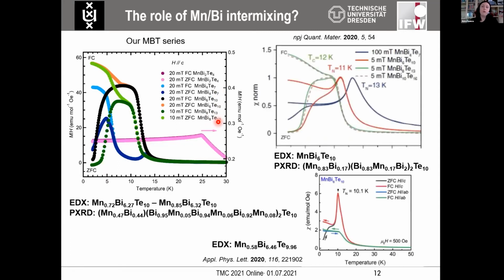However, when we looked at the data reported by the other groups, we started to notice a lot of inconsistencies in this elucidation. So many other groups, so I only chose two examples here because there was also a characterization of the composition and structure. So many other groups observed that in fact 1610 phase is looking like an antiferromagnet, more or less.